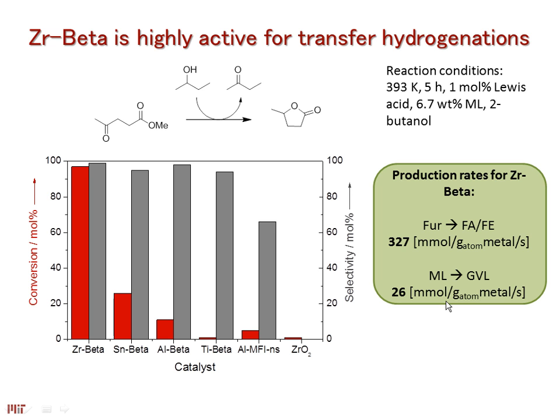So the very first thing that we did, we just wanted to look at the proof of concept. We started screening catalysts in a batch system. So for example, a catalyst containing zirconium, such as zirconium beta, is very active in this particular step, taking levulinic acid or methyl levulinate or butyl levulinate in the presence of a secondary alcohol or a primary alcohol. Actually, a lot of different alcohols work for this step and produce GVL. Production rates are good, but for this particular step of methyl levulinate to GVL, they're much lower than for the initial step, furfural to furfural alcohol, which I'm not showing here. But what I want you to remember is that our zirconium beta appears to be the most active catalyst for this transformation.